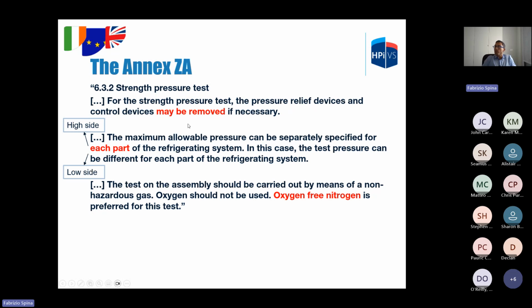As a general note, for the strength pressure test, safety devices may be removed if necessary. The pressure test for each side can be made separately, so one test for the high side and one test for the low side. The preferred fluid is oxygen-free nitrogen.